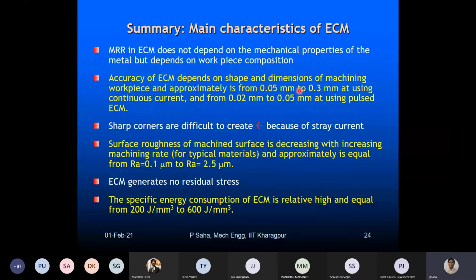And accuracy of ECM depends on the shape and dimension of the machining of the workpiece. Approximately it is from 0.05 to 0.3 millimeter using continuous current. But compared to a continuous source, pulse voltage will give you better accuracy. Why? Because with pulse voltage the entire charge is segmented into a number of pulses, and for every off time you get some time to restore the inter-electrode gap towards its original conditions in terms of ion concentration, temperature, and reaction products removal, so that your dissolution rate across the gap remains uniform.